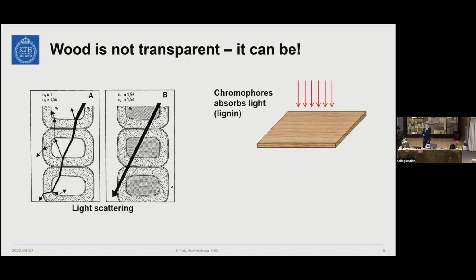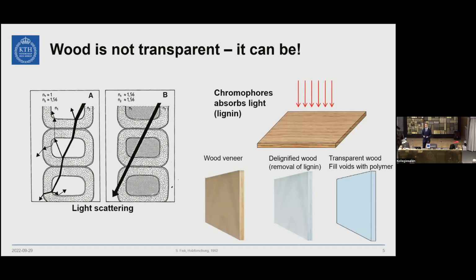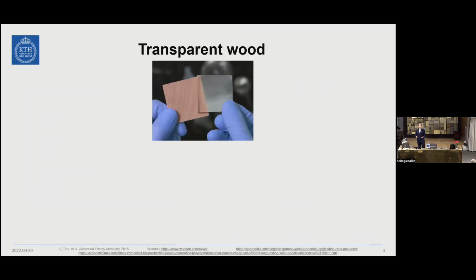One of the reasons is that there are some compounds in wood that actually absorb light, for example, lignin. So one idea is that we take the wood veneer, remove the lignin by delignification, and then fill the pores with the polymer. And then we can make it transparent. I can show here the difference between the two. So you can have a transparent material and a translucent material without the delignification.